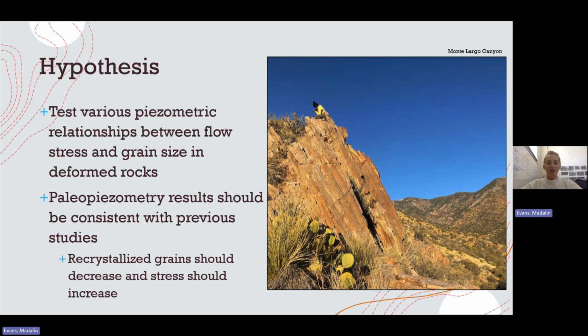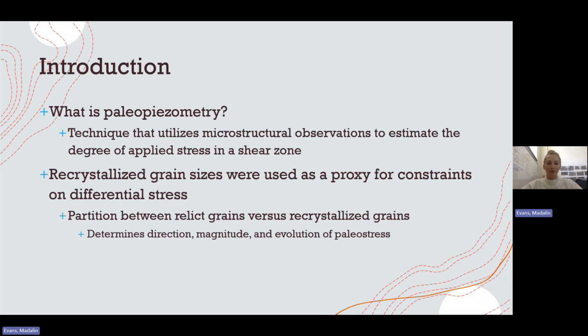We had proposed to test various piezometric relationships between flow stress and the grain size in deformed rocks. Paleopiezometry results should be consistent with previous studies by having a linear relationship between the recrystallized grain size and paleostress. Recrystallized grains should decrease and stress should increase, getting closer to the shear zone via dislocation creep. This should display the appropriate recrystallization mechanisms dependent on their location relative to the shear zone.